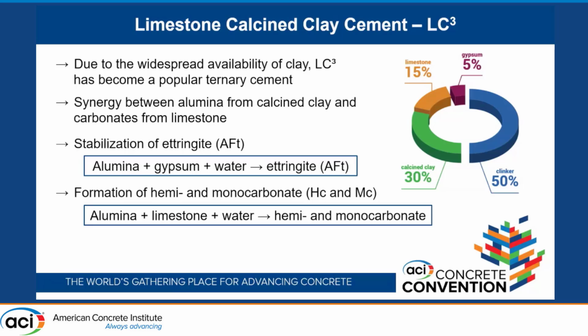And besides the pozzolanic reactivity here, we're also able to take advantage of the synergy that we have between alumina and the limestone. So some of the things that you can see with LC3 is the formation and stabilization of more ettringite, which can help with the packing density, as well as the formation of new hydration products like hemicarbonate and monocarbonate that have higher bulk modulus, so they can help with the performance as well.